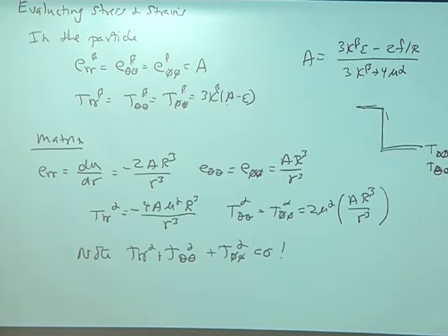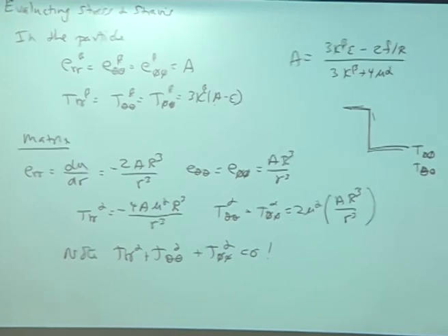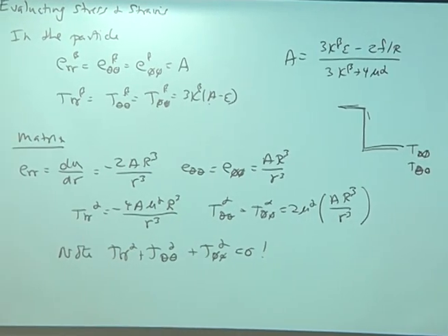T RR would also jump if the surface stress is non-zero, but because of the force balance, T RR is continuous. But T theta theta can jump.